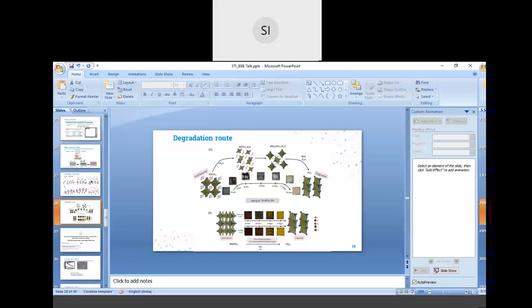Okay, there's another question from Kiran KS. He's asking the Goldschmidt tolerance ratio of lead chloride and lead acetate perovskite. Gold means you are talking about the counter electrode? No, he is asking the tolerance ratio of lead chloride and lead acetate perovskite. Goldschmidt tolerance factor, okay. So for lead chloride it is very close to 1, almost 1. And for lead acetate and the two-step route, it is close to 0.9, 0.92, 0.93 like that.